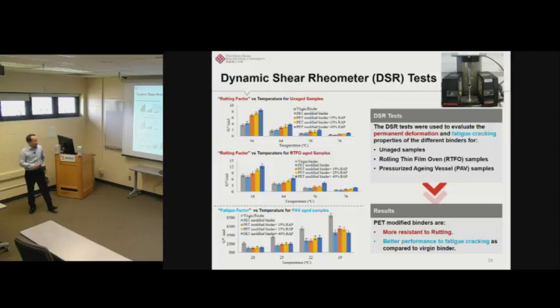So through the DSR test, our findings are, first, the PET additive's effect on the rutting factor is not significant. But the binders with both PET additive and the wrap binder are much better than the virgin ones. And for the fatigue, we can see the PET additive can significantly improve the fatigue performance of the binder.